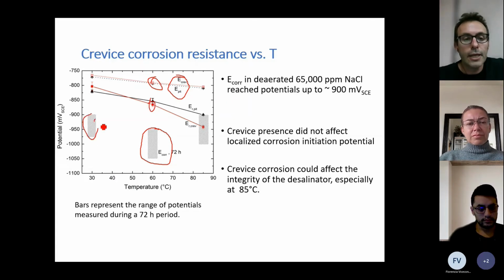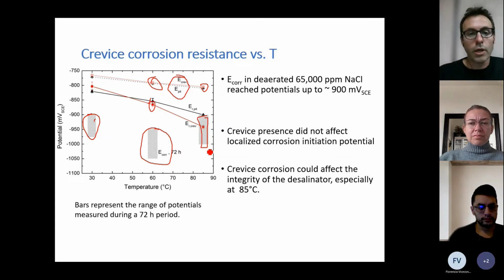So what we see here is that at 30 and 60 Celsius, the plant should be okay. And when we go up to 85 Celsius, the open circuit potential is on the same order as the repassivation potential. Still smaller than the initiation potential, but on the same order as the repassivation potential. So the takeaway point of this is that we must not permit localized corrosion to initiate, because it might be very difficult to repassivate it, considering that the repassivation potential is close to the open circuit potential.